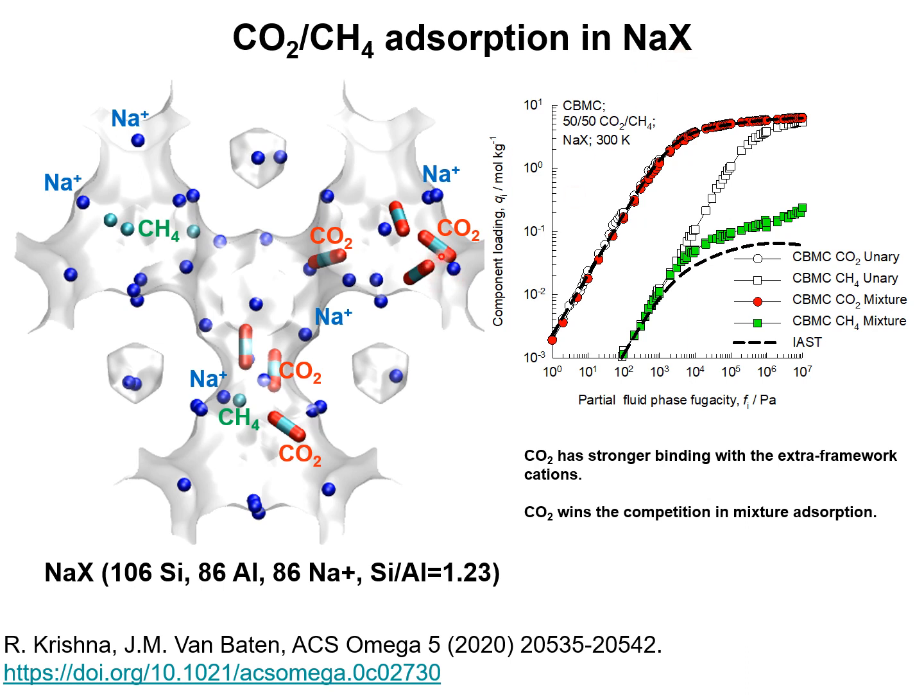The CO2 molecule experiences strong electrostatic interactions with the extra framework cations, and they congregate around the sodium cations, leading to an inhomogeneous distribution of the guest molecules CO2, methane within the pore space. Due to this inhomogeneous distribution, the methane molecules face a less stiff competition with CO2 than would otherwise be the case if the guest molecules were homogeneously distributed.